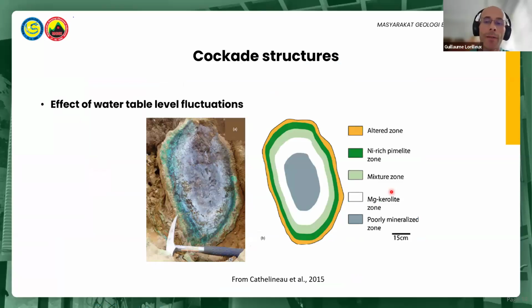Mineralized cockade structures have been described in New Caledonia, with mineralized silicates in thin layers cementing joints. Their chemical and mineralogical concentric zoning has been interpreted as resulting from nickel remobilization related to active dissolution-precipitation processes of nickel-rich veins. These processes would be caused by evapoprecipitation processes related to alternate periods of hydration and drying induced by water table movements. And similar features have been described also in the clasts of the collapse breccias of endokarst features.